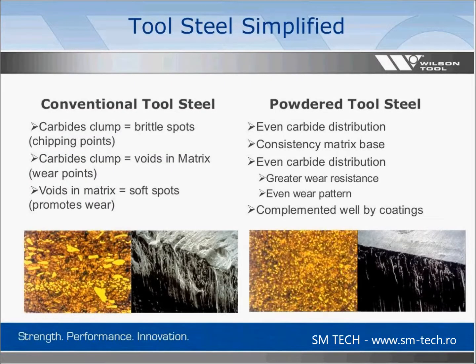There are two basic types of tool steels that you'll hear about out there. There are conventional tool steels, and then there are powdered tool steels, also known as powdered metallurgy. They're classified by how they are manufactured. In conventional tool steels, due to the manner in which they're manufactured, carbides can tend to clump together. When carbides clump together within the matrix, it creates brittle points within the matrix. Because carbides are a percentage of the matrix and that doesn't change, when the carbides clump together, it also creates voids in the matrix, or soft spots. Those actually wear faster, and the brittle spots from the carbides clumping are chipping points, so another form of wear. Again, voids in the matrix equal soft spots and promote wear.